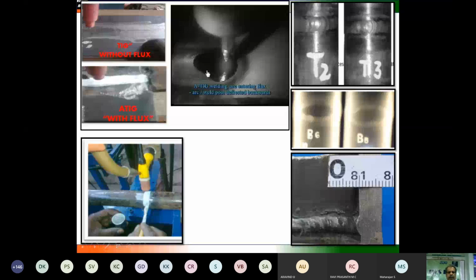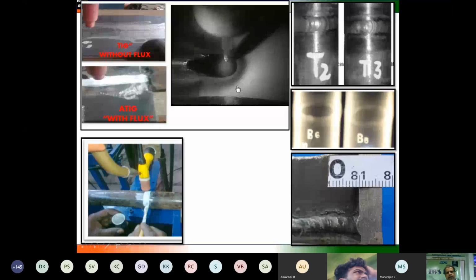The bead width becomes narrower, and the penetration becomes deeper with a shallow bead width, and because of that the welding can be done very easily, and with high penetration, high thick wall tubes can be welded in a single pass. That is the major advantage of the process.